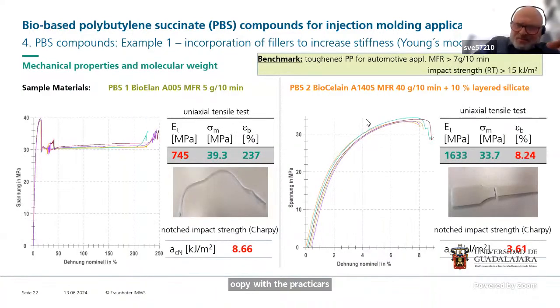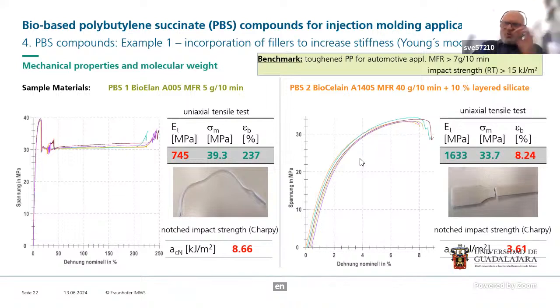But the problem is, you will see that here in the comparison. That is the pure PBS that you have seen earlier. And this is the PBS with the additive. So what we have achieved now, we have dramatically increased the modulus, the stiffness of the material. The stiffness of the material is doubled now. It's beautiful because we have this beautiful porcelain-like, really nice and stiff material, but we are losing the toughness.